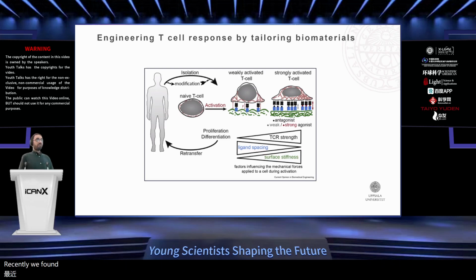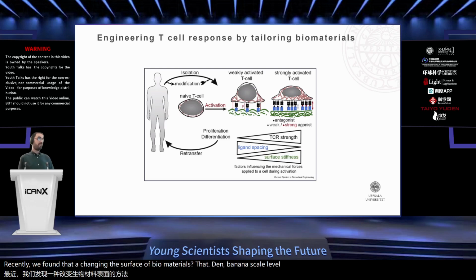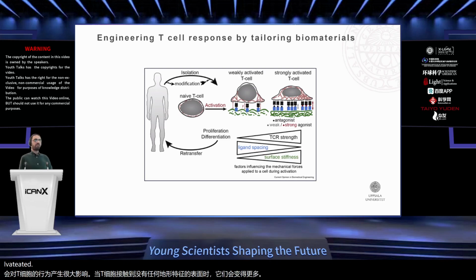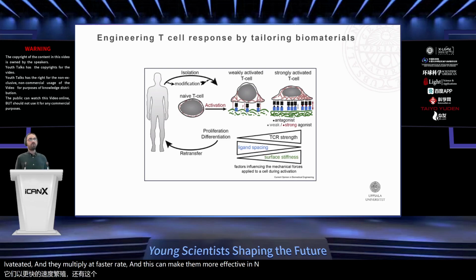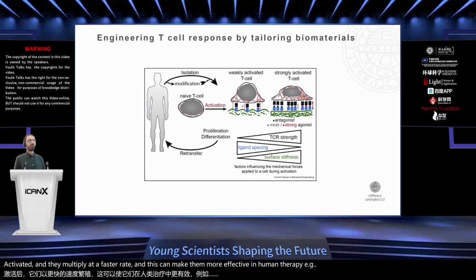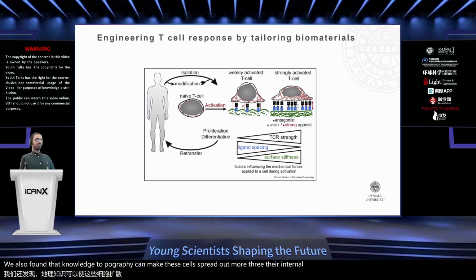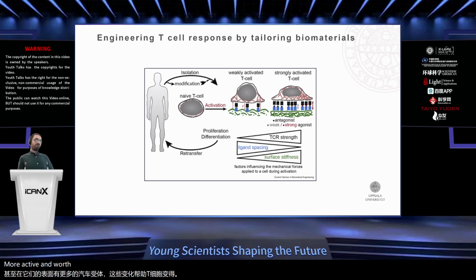Recently, we found that changing the surface of biomaterials at the nanoscale level can have a big impact on how T cells behave. When T cells come into contact with surfaces with nanotopographic features, they become more activated and they multiply at a faster rate. And this can make them more effective in immunotherapy, for example. We also found that nanotopography can make T cells spread out more, rearrange their internal structure, and even have more CAR receptors on their surfaces. And these changes help T cells become more active and work better against tumors.